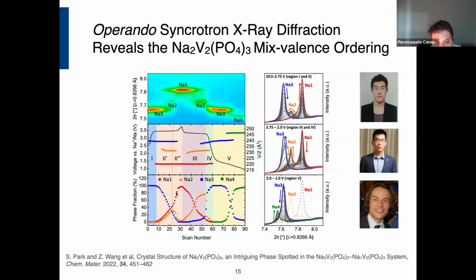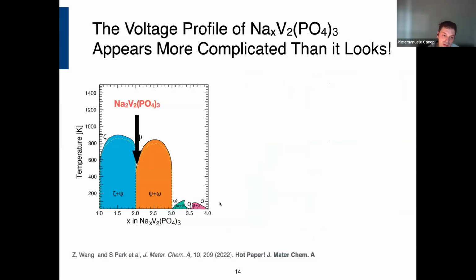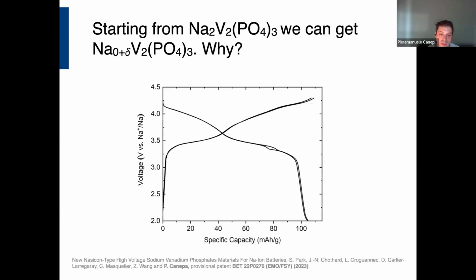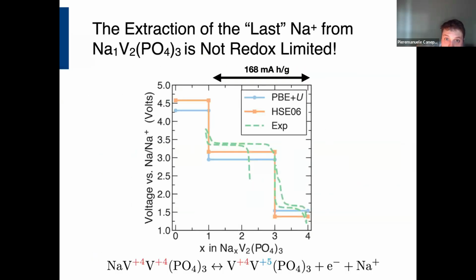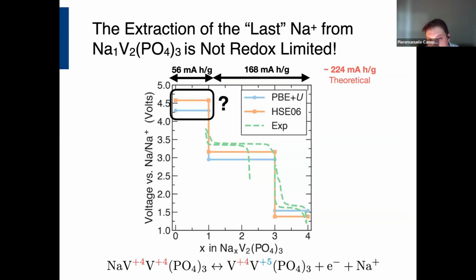So then they went to the lab. As I said, this is the one that they discovered by extracting the sodium from sodium 2, but they can also go to the lab and really reproduce the phase diagram, right? They take the sodiated material at x equal 3, they take the material at x equal 1, they work at the proportion of x equal 2, they combine it at high temperature, they make the synthesis, and they get a new sodium 2 phase. And now, look, discharging from the sodium 2 phase, they can effectively extract all the sodium ion from this NVPO4, effectively achieving what I was trying to show you from a theoretical perspective, the theoretical capacity. So there are ways in which you can synthesize this material, and depending on which phase you start with, you can access capacities and extract all the sodium, which is quite intriguing.